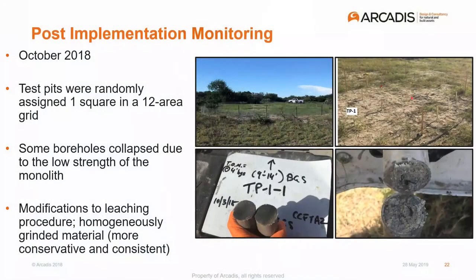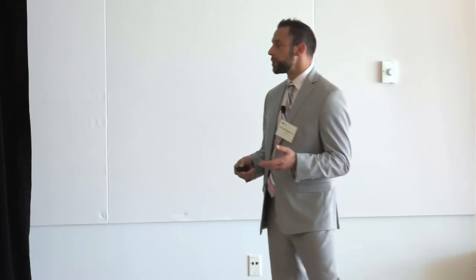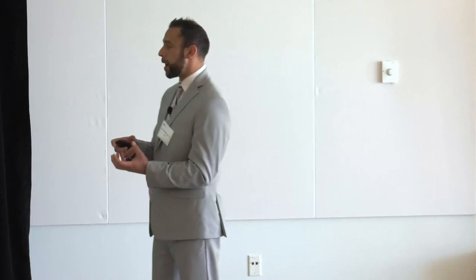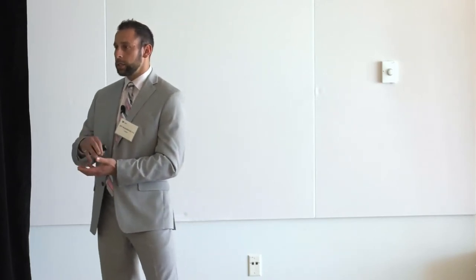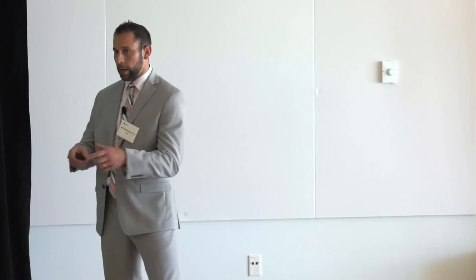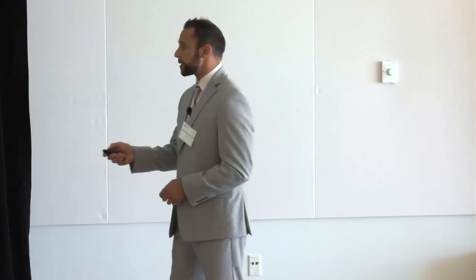Some of the borings had lower strength, right? Whether that was the antagonistic effect of the fixin or whether it was poor mixing, we don't know. But we modified our leaching procedure and didn't do intact cores like Chadi did. Instead, in our treatability lab, when we received the soil samples, we ground them to a uniform, I think right around a 200 sieve type perspective, and then sent that to the lab for leaching. And that's permissible under the 1315 method, which has an accommodation for almost like a minor bucket that you would pack your crushed material in and then sequentially leach that little bucket through each of the leaching steps. So that's the way that we went about it.